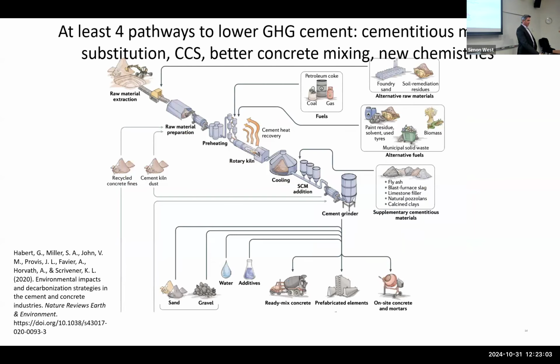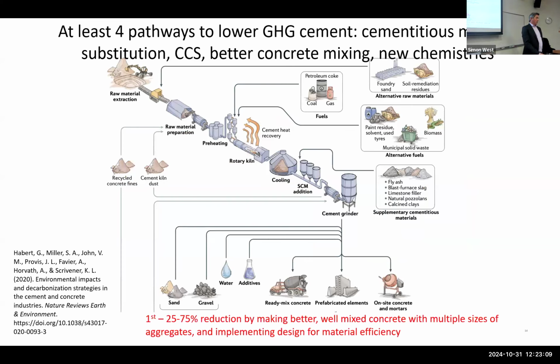Now, the key thing with the cement sector, and this is a beautiful article, it's Habert et al. 2020. I love the drawings. The key thing here is we tend to make bad cement. We tend to make very GHG intense cement with a lot of clinker in most of the OECD countries. Just by using 3 or 4 sizes of aggregates, and using dispersants to minimize the amount of cement you need to hold the sand and gravel together, you can probably get a 25 to 75% reduction in the amount of clinker you need, which effectively means a 25 to 75% reduction in the amount of CO2, because that's where most of the emissions are from.